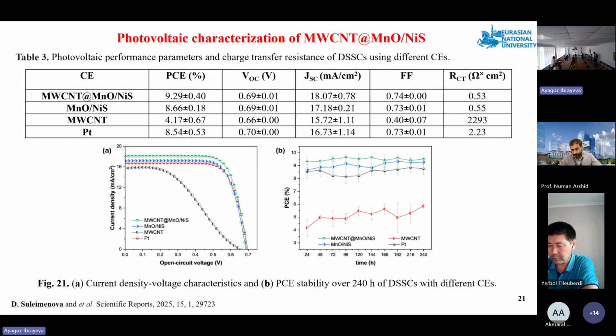Photovoltaic efficiency and stability of the composite. The ternary composites achieved the highest DSSC efficiency of 9.29%, outperforming the platinum electrode at 8.54% and the binary composite of manganese oxide and nickel sulfide at 8.66%. In contrast, using only multiwalled carbon nanotubes resulted in much lower efficiency, 4.17%, due to high resistance and low catalytic activity.